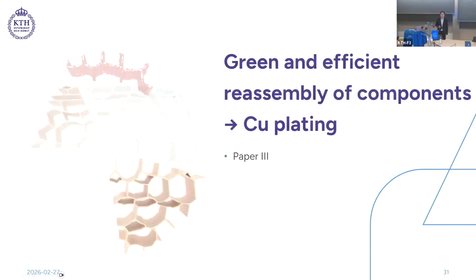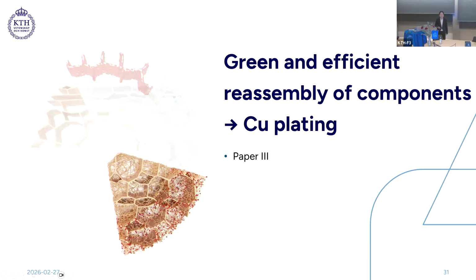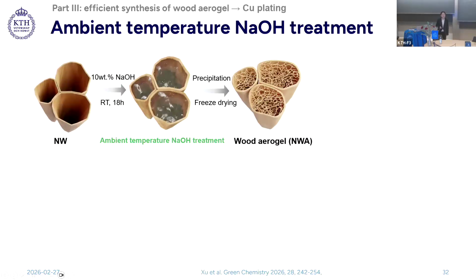In part 3, we shift toward a more sustainable alternative. A one-step green and efficient approach was developed to both increase the porosity and utilize the lumen space. Copper plating was then investigated to impart new functions. Here, a one-step ambient temperature sodium hydroxide treatment was used to produce native wood aerogel.